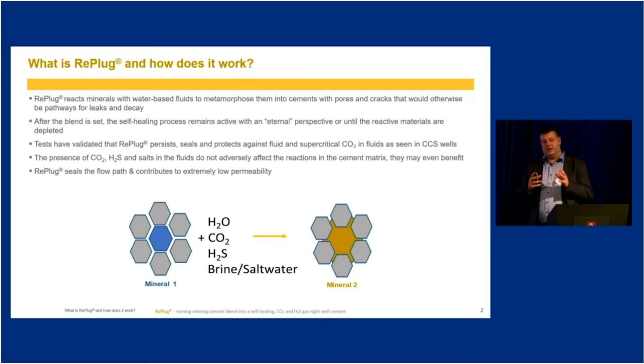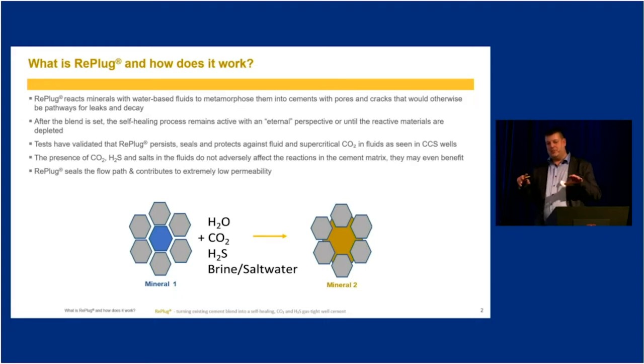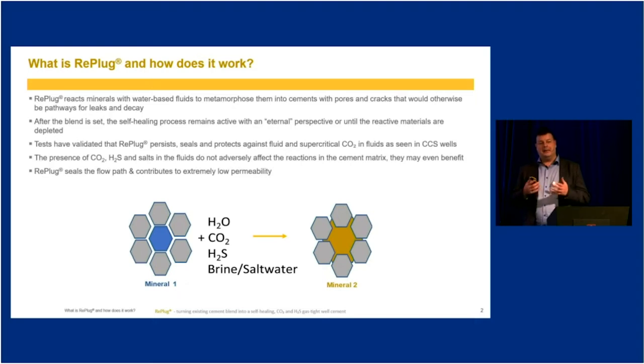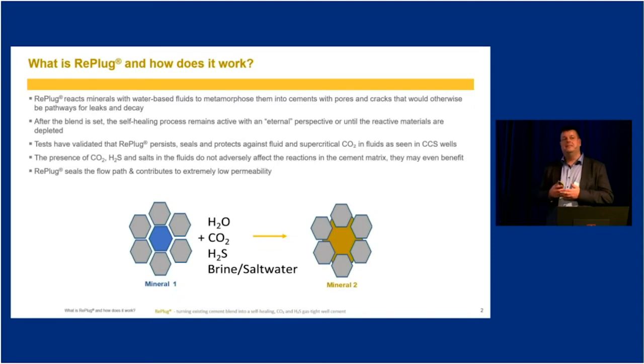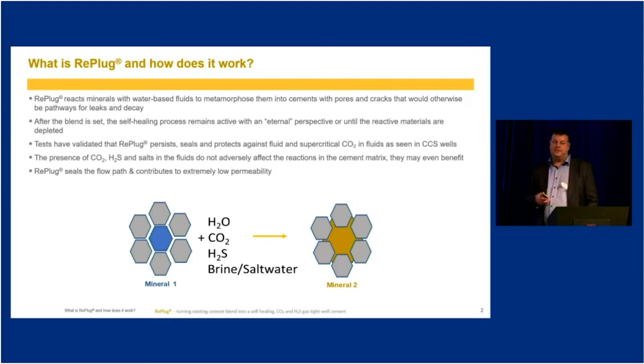Put it another way, if it's exposed to CO2, water, pressure, or temperature, it will expand and close the voids or any leaks you have in the cement, and then it will seal off, and the process stops. So let's say you have a mini earthquake, or you have a tubing that is expanding, or a casing that is expanding due to thermal effects. If the cement cracks, you get what we call microannuli, and it will start to leak, it will activate our mineral, it will seal, it will re-tighten, close the path, and it will stop. And that will continue on and on for eternity.